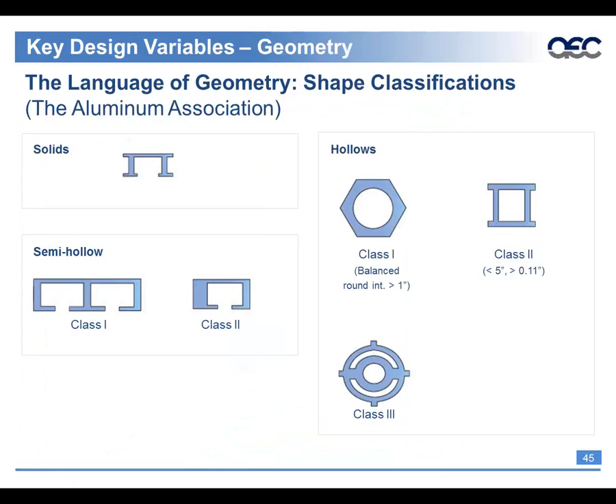Semi-hollows. While not quite a fully enclosed area, you have a hollow area in there that has a very small tie-in to the exterior of the shape. There are two types within the semi-hollow consideration: Class 1 and Class 2. Class 1, real simple, just means it's a balanced semi-hollow. You can see all the wall thicknesses are consistent and the semi-hollows are the same size. Class 2 typically means you've got an offset, dissimilar wall thicknesses. You can see on this, the left wall is thicker than the right wall, and both the left and right walls are thicker than the bottom and top walls. So it's basically an unbalanced shape.